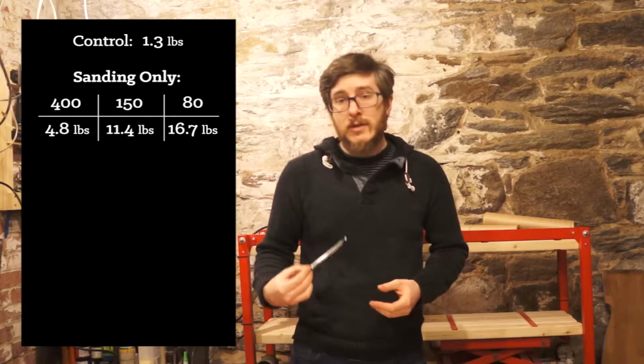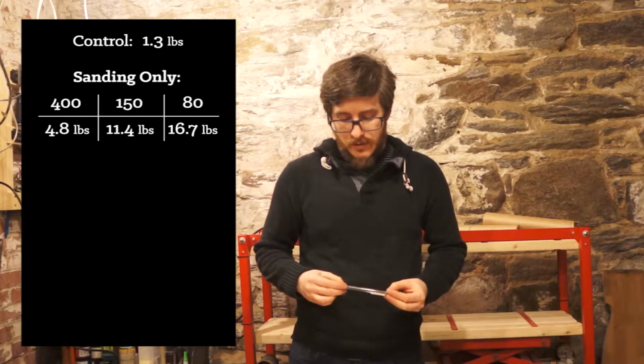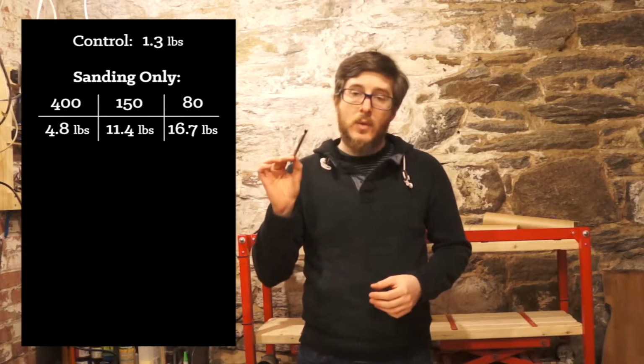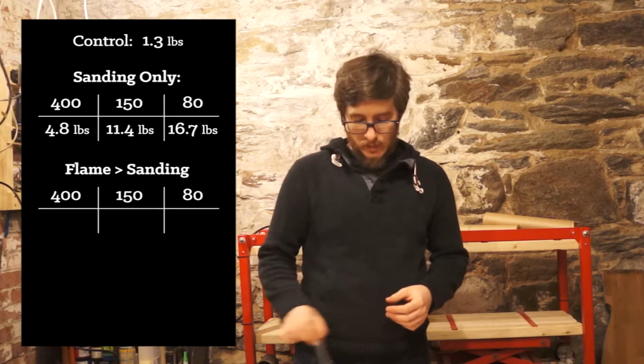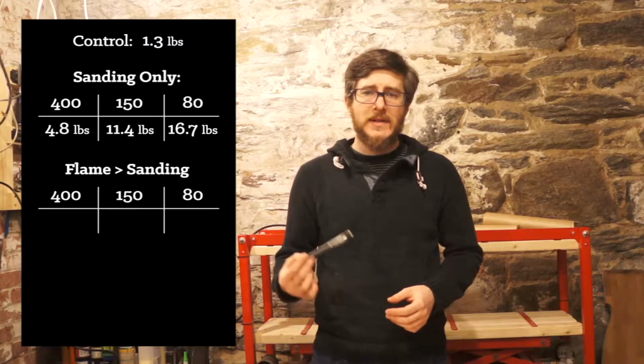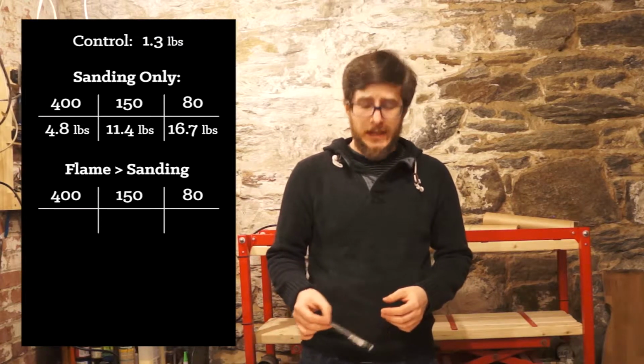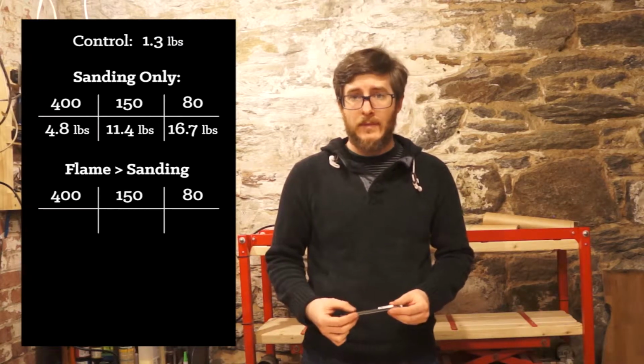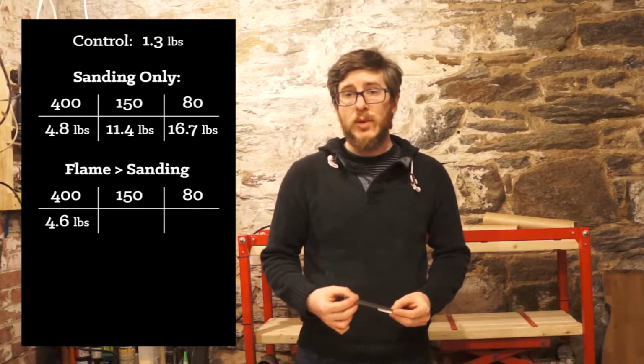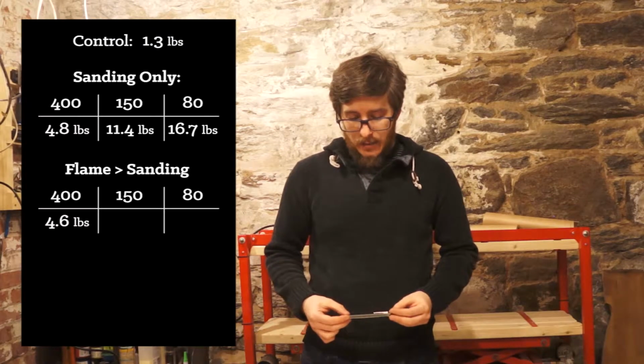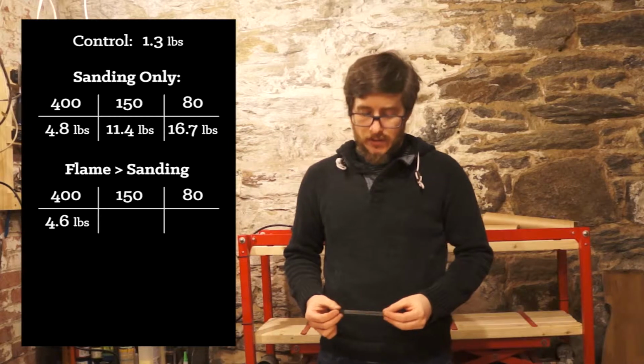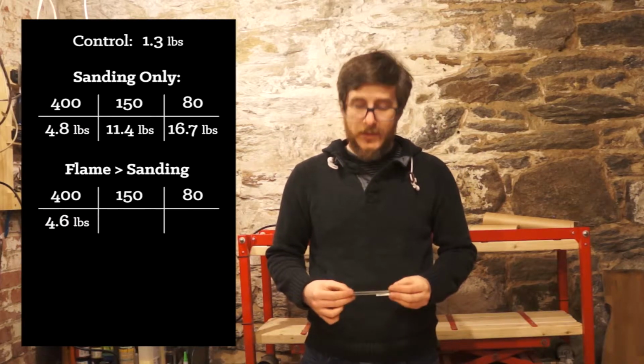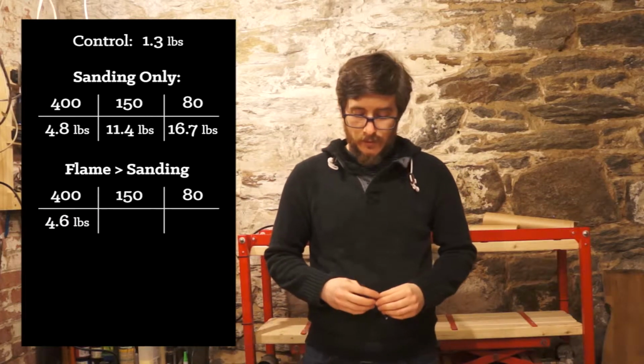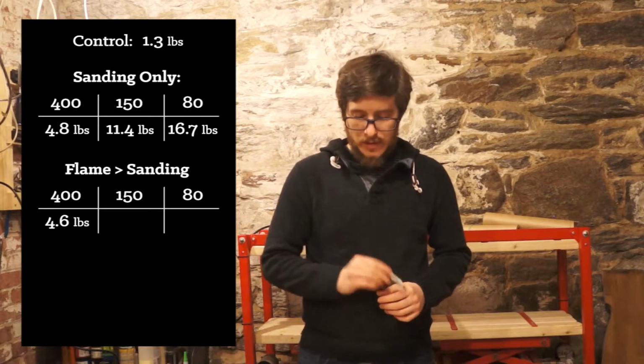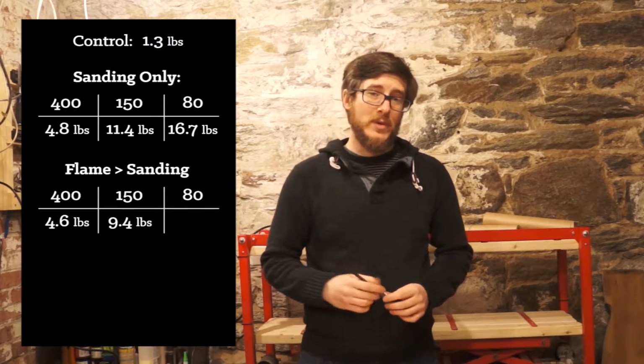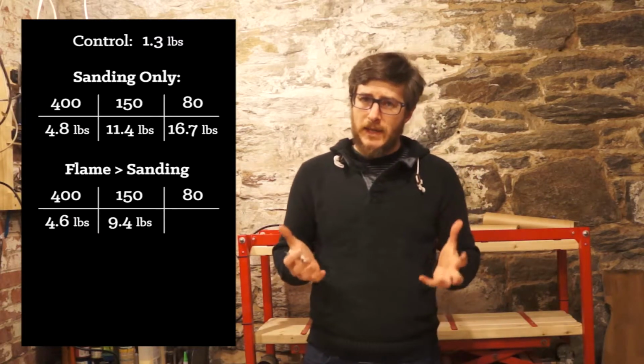And that trend continued as we went through our other sets of flame treatments. For the set where we flame treated the plastic before sanding, the 400 grit was actually less well bonded in this one case than the sample that wasn't flame treated, coming in at 4.6 pounds. We saw that trend continue with 150 grit, where for the sample that wasn't flame treated, we were at 11.4. For the sample that was flame treated before sanding, we were at 9.4. So 2 pounds weaker in its bonding strength.